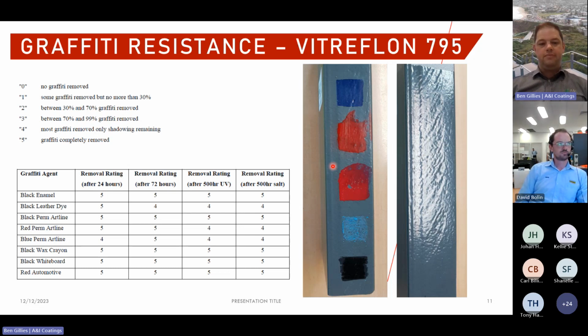Now, when we test for graffiti, we test a range of different types of graffiti, which can be seen in this column here. We test the removal rating, with 5 being complete removal and 0 being impossible to remove. And then what we also do, we leave the graffiti on there for certain amounts of time. So in this column here, you can see we've applied the graffiti, then we've placed the sample with the graffiti in our QUV machine for 500 hours, and also in our salt spray cabinet for 500 hours. And you can see some of the types of graffiti became a little bit harder to remove, but they all still remove quite easily, because the longer you leave graffiti on a substrate, the harder it is to get off.